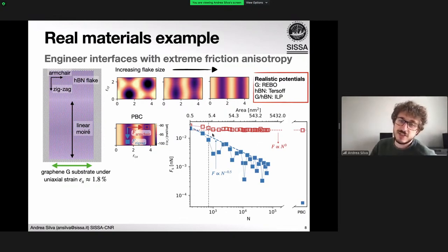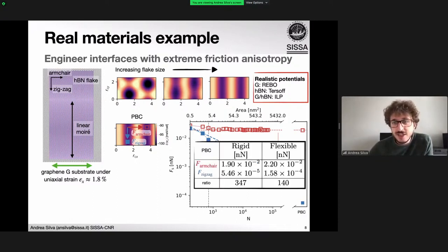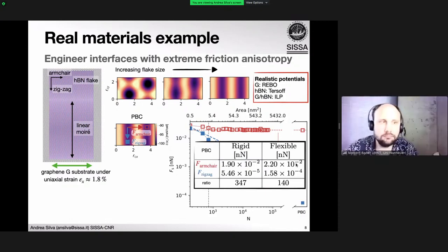So the system shows constant friction perpendicular to the valley and goes down sublinearly in the other direction, realizing in the infinite system a very strong anisotropy and structural lubricity only along one specific direction. Using numerical simulation, we can also probe the effect of elasticity, which of course affects the whole system, but this behavior is still retained.